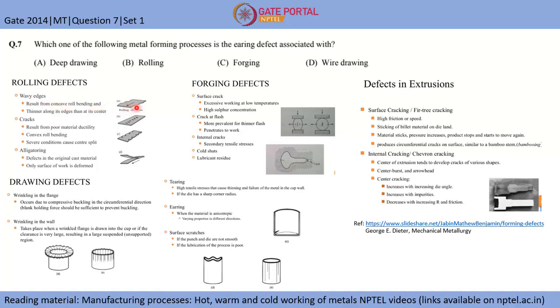So, wavy edges on the sheet are formed because of rolling and concave roll bending, and the sheet is thinner along its edges than its center. So let's say if I have two rolls which are concave, then the center will have higher thickness, and the edges will have lower thickness. And cracks are generated, like you can see, these are the center cracks and these are the edge cracks. The edge cracks result from poor material ductility. Let's say my material is magnesium and I want to pass it between the rolls. Magnesium or any HCP material has poor ductility. Hence these types of cracks can be observed here.